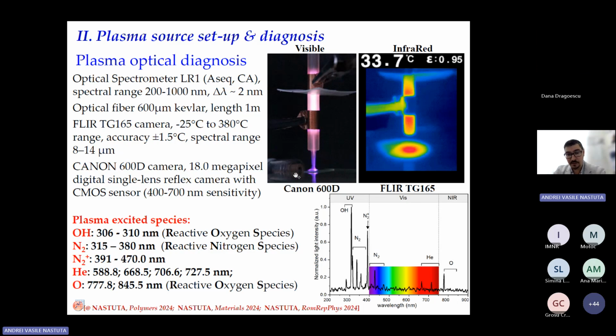Here we have a sheet of polymeric foil, and it is exposed to the plasma. Beside this optical image, we have an infrared image, and we can tune up the electrical parameters of the plasma in such a way that we can get even a cold discharge. The red color in this infrared picture is the highest temperature. So we can have such a situation in which we can say that this discharge is cold, but also we can make it hotter.